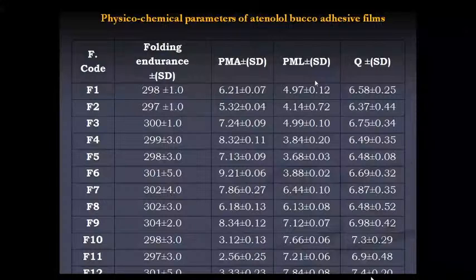And PMA is the percentage of moisture absorption. So you need to check the film stability in the highest moisture condition, whether the film is stable in the high moisture condition or not. And PML is nothing but the percentage of moisture loss. Again, this test is useful to check the film integrity in dry condition, whether the film is holding its integrity or not.